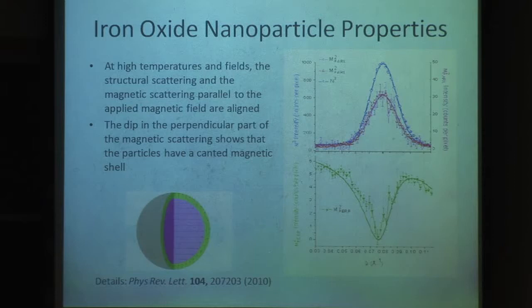However, our perpendicular scattering had a very different shape. It has a nice dip as opposed to that peak. That dip corresponds to a single shell model. And because that dip is opposite of our peaks, we got the idea that there's a canted magnetic shell model, which means that there's one direction, which is our general magnetic moment, and then on the outside, there's a shell, which has magnetic moments pointing in the opposite direction, as seen here.